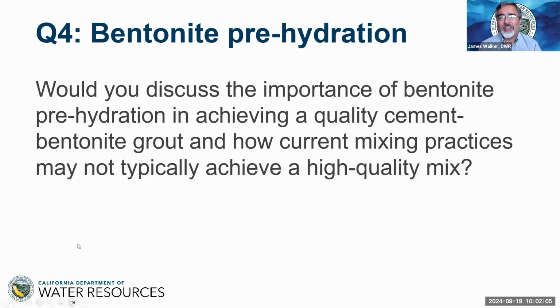Thanks, Julie. So bentonite is traditionally added to cement-based mixes per Bulletin 74 up to 6% by weight of cement, used to improve fluid characteristics of the sealing mix and reduce the rate of heat generation during setting. You've explained the benefits, Donald, of mixing cement with high-speed, high-shear mixers and how bentonite as an additive can enhance certain properties of cement to allow increased water content without increasing bleed. Would you discuss the importance of bentonite prehydration in achieving a quality cement bentonite grout and how current mixing practices may not typically achieve a high-quality mix?